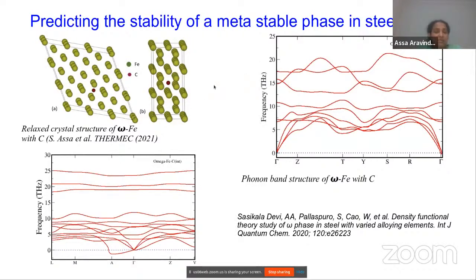So to analyze the stability of it, we have calculated the phonon band structure, as you can see here. And the presence of this metastable phase is caused by the presence of interstitial carbon. So we simulated the system by iron, hexagonal iron with interstitial carbon, and also with many other alloying elements such as silicon, whatever is possibly in it, because the steel makers know what the concentrations of alloying elements inside it are.